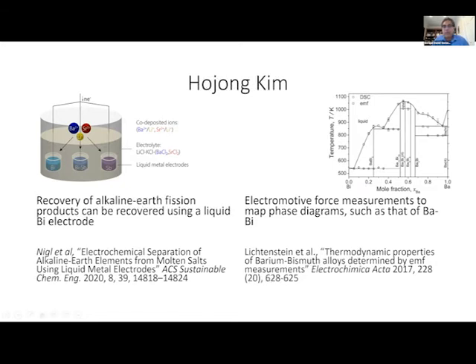And so, for example, in this case, he demonstrated that he could make a very accurate phase diagram of barium bismuth and even identify new phases of barium bismuth at very specific compositions that otherwise you just can't do using other approaches. And so he's essentially a leader in using electrochemistry to be able to develop the phase behavior of some of these molten salts. And these are important, again, for some of these electrochemical systems that he's designing, for example, for resource recovery, plus other types of metal applications.